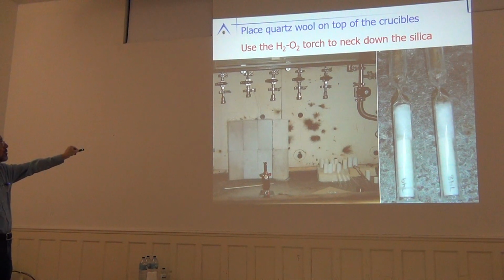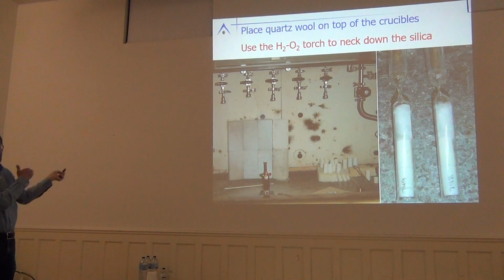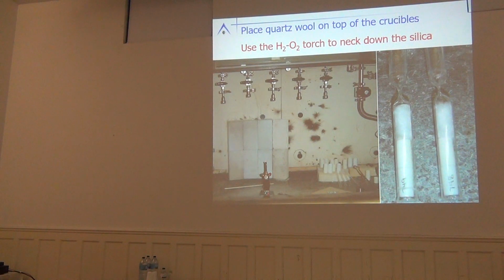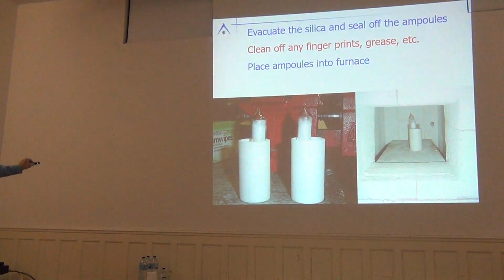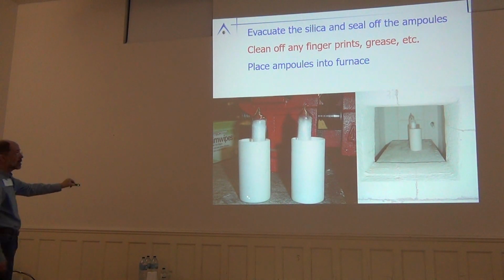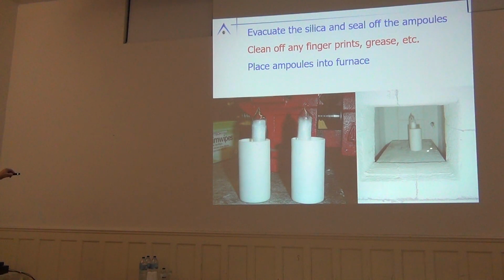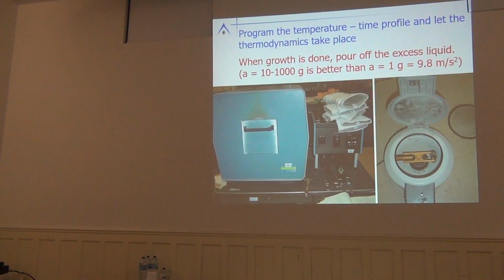I hook this up to a pumping manifold. I pump it out. I flush. I pump, flush. I backfill with a tiny bit of argon. And then I take the torch. I seal this off. And I now have my ampule. I have it in a larger crucible just so it stays upright in the furnace. Here's the furnace area. This can heat up to 1,500. For this growth, I'll only be going as high as 1,200. That's a little thermocouple in back to keep track of temperature. I program the temperature profile I want, and I heat up. I go to a maximum temperature. I slowly cool down.